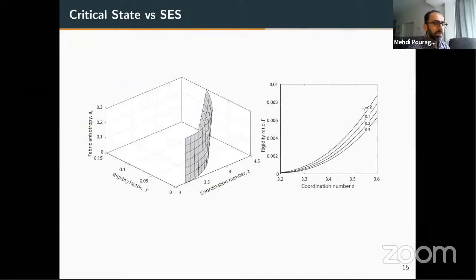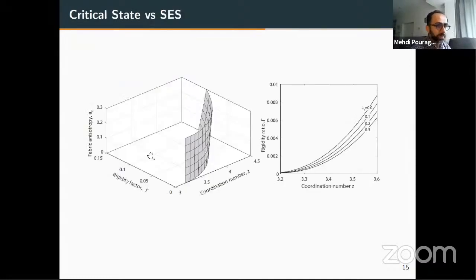Okay, the relation to critical state can be shown a little bit more. The critical state, if you remember, was a line which related the hydrostatic pressure to the porosity or void ratio of the volume. Now, if we take this manifold and we project it on the horizontal plane, we get contours of constant fabric anisotropies. And if you remember, the rigidity ratio, as I mentioned, is proportional to hydrostatic pressure, and coordination number.